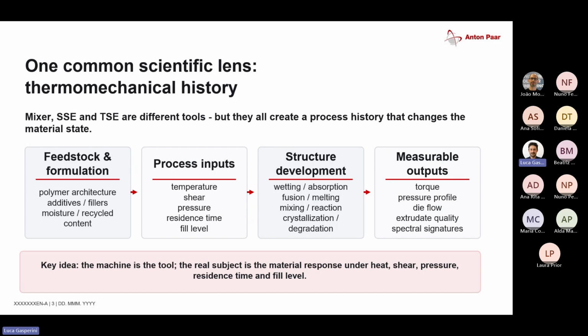So to observe these mixing behaviors, we can adjust input variables such as the temperature. We can apply shear stress by changing the speed of the blades or of the screw. We can change the pressure by adjusting the screw configuration, or also aligned with the speed. We can increase the residence time in a batch mixer or in the extruder by adjusting the screw configuration, and we also have an input on the fill level of a screw or in a mixer.